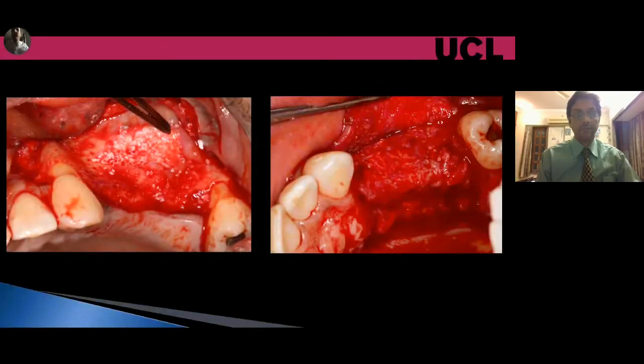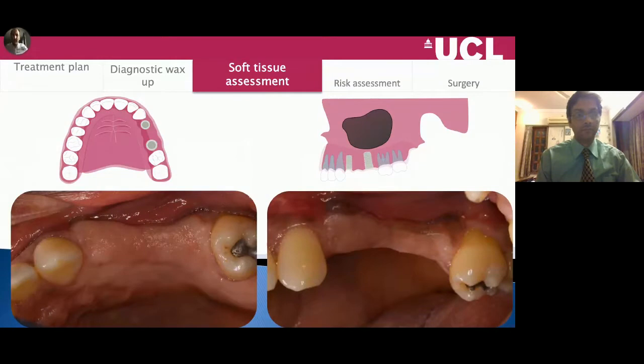This is again the pre-op, or the intra-op, before placing the titanium mesh. You can see the thin ridge, and then how it healed over time at 9 months when the re-entry surgery was done, how we had gained a significant amount of width and height. Now this case is absolutely ready to receive a dental implant on the upper left 4 and the upper left 6 position. We have gone from a situation where it would have been impossible to place any implants to a situation where it would be very predictable to place dental implants to replace the missing teeth.